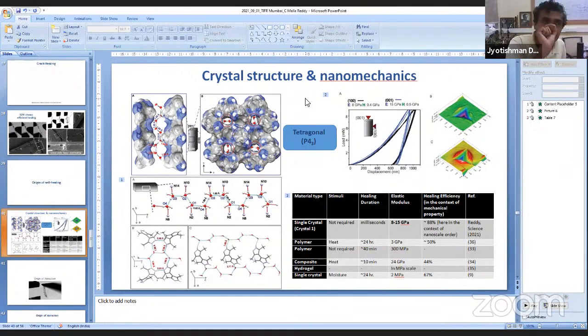So if a similar experiment could be planned where you remove a monolayer of molecules or a bilayer of molecules from the crystal and then again reform it, it would almost serve like an isotherm. You can measure the binding isotherm of such an event. That could be one possibility of looking at the interaction energies. The other one is a macroscopic experiment. Break two crystals and see if you can bring them together.